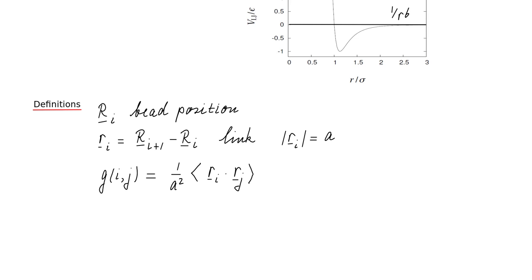Then we define g_ij, which is 1 over a squared times the expectation value of the dot product between r_i and r_j, and this is the so-called correlation function. It's the correlation function for the orientations of the links. What we expect is that if there is no bending interaction, no dihedral interaction, then this will decay very quickly. And if the bending interaction is very strong, then this will decay very slowly. But because the chain is essentially one-dimensional, there is always an exponential decay that we expect for this g_ij. So we expect this to decay like e to the power minus